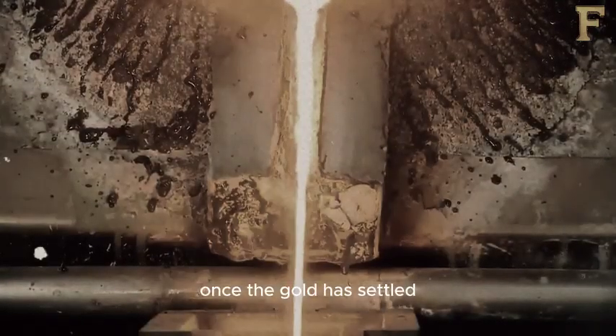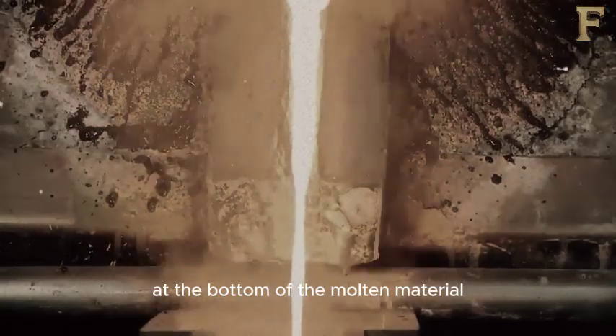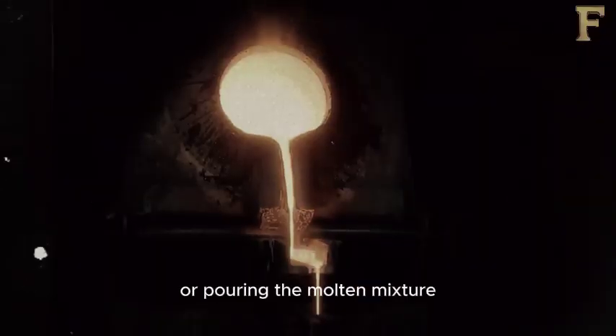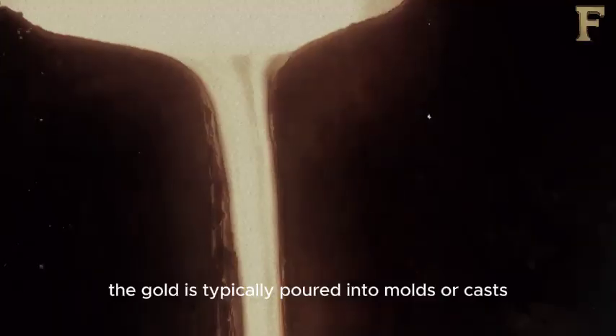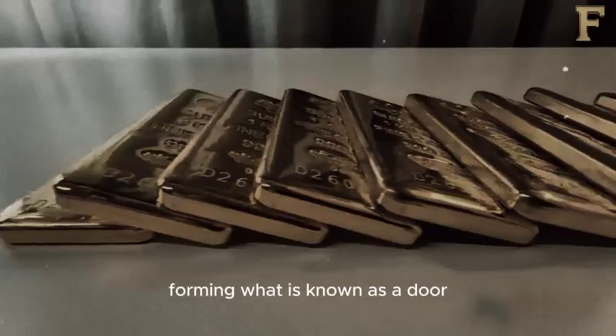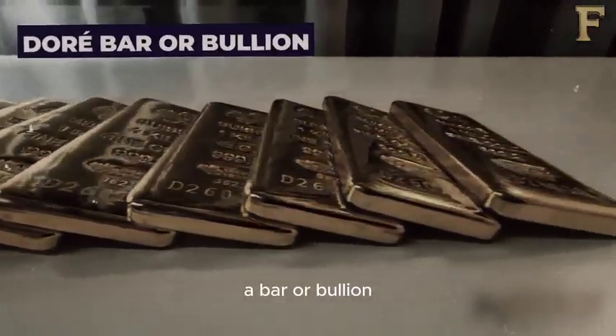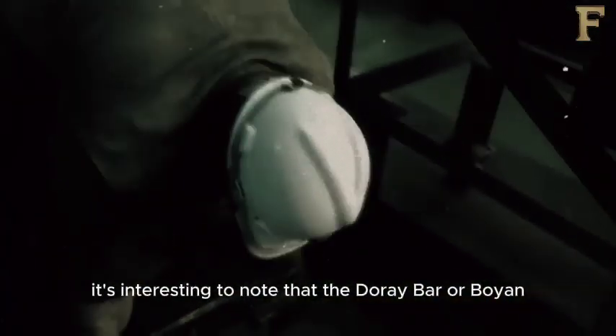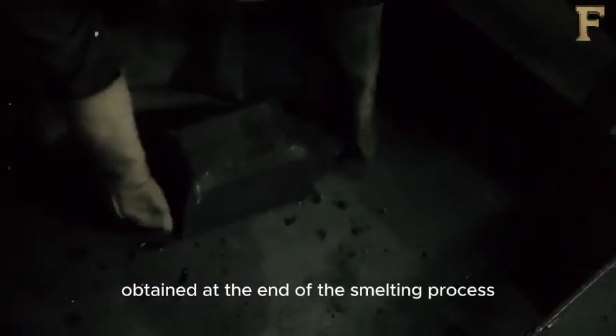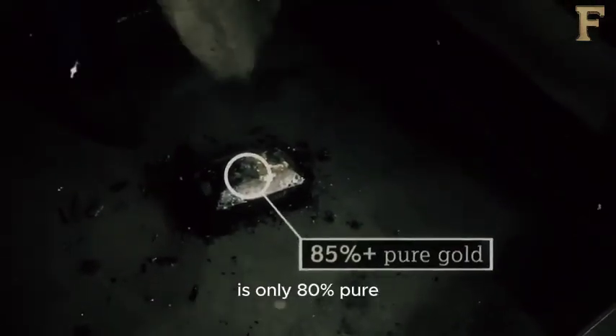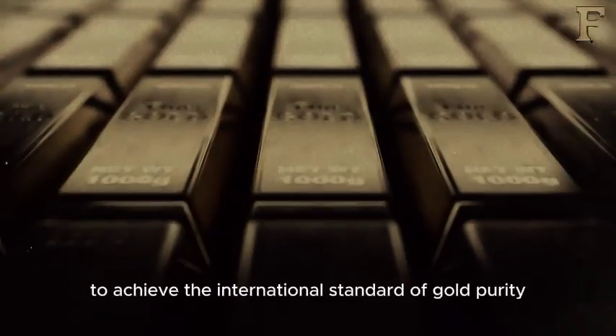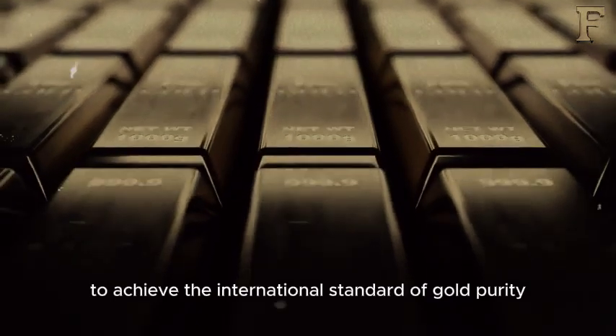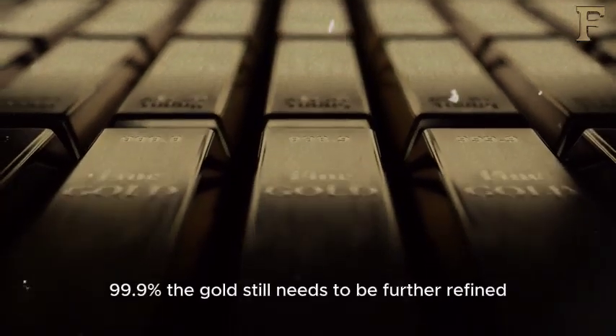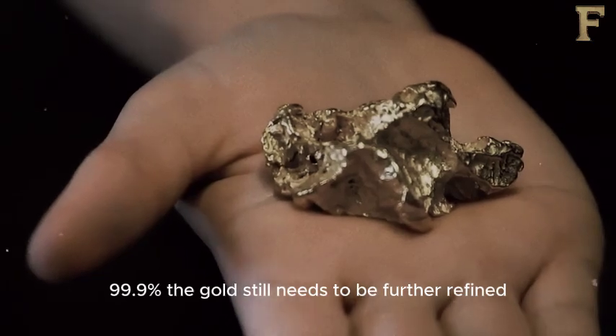Once the gold has settled at the bottom of the molten material, it is collected by tilting or pouring the molten mixture. The gold is typically poured into molds or casts, forming what is known as a doré bar or bullion. It's interesting to note that the doré bar or bullion obtained at the end of the smelting process is only 80% pure. To achieve the international standard of gold purity, 99.9%, the gold still needs to be further refined.